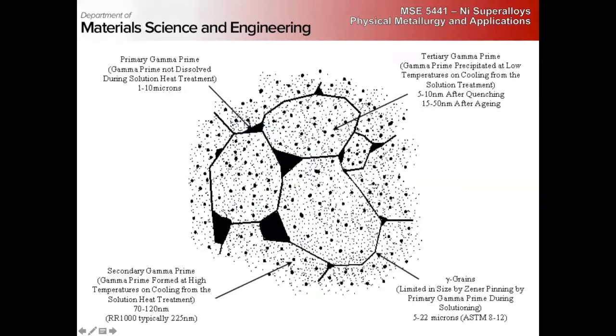And then the smallest precipitates precipitate at lower temperatures on cooling from the solution treatment. And these are going to be tertiary gamma prime, and they're going to be on the order of 5 to 10 nanometers, right? So it's a heterogeneous multi-scale distribution of strengthening, right? Typically, these will then go through an age treatment, and the tertiary gamma prime will grow to 15 to 50 nanometers, right? So a very fine scale, right?